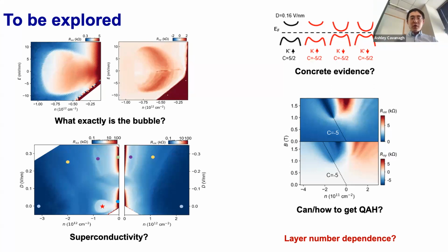Our observation is that whether you choose the butterfly or the M shape, no matter which one it is, the amplitude of Rxy is already maximized. There are no steps to jump once and twice. So most likely this whole thing got pinned and then flipped as a whole instead of gradually changing, based on our observation.